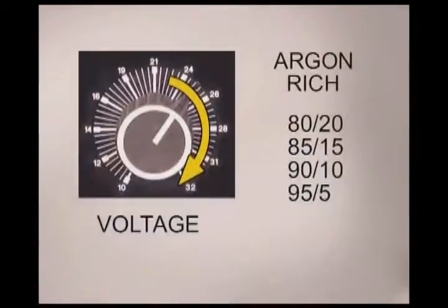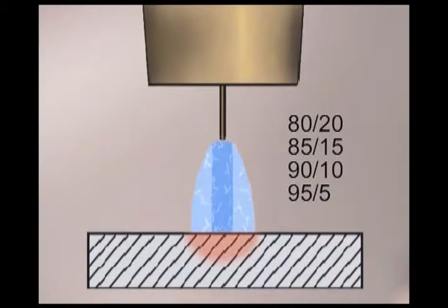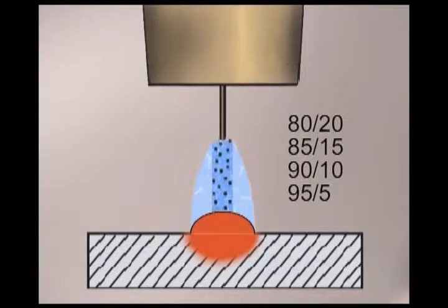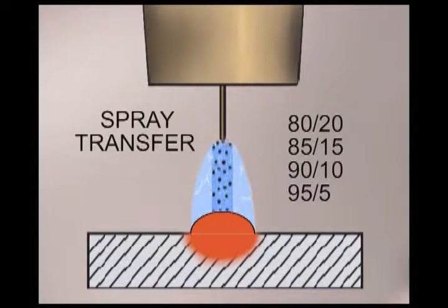Here's where all those different shielding gases come into play. By switching to an argon-rich gas at the higher voltage range, the dense, concentrated arc stream causes the filler metal to break up into smaller pieces. This is called spray transfer. The small pieces are sprayed across the arc stream into the molten puddle. This is the wire feed process typically used for the efficient, high-speed production welding of metals up to 3/8 of an inch thick. Here again, because of the amount of heat and weld metal, spray transfer is generally used only when the weld can be positioned flat.